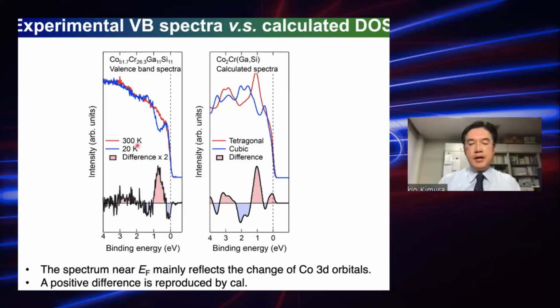So now we again compare the result between theory and experiment. We see again the difference between the 300 Kelvin and 20 Kelvin density of states. You see the negative difference near the Fermi energy and the positive difference at 0.7 eV. This behavior is overall reproduced by the calculation, but there is a little difference near the Fermi energy. In the calculation, you have a positive peak here. This suggests that there is some difference in the Fermi energy position between the calculation and experiment. When you move the Fermi energy in the calculation to a slightly higher binding energy, the theoretical band structure reproduces the experimental result very well.